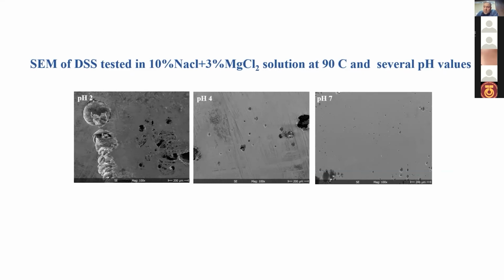Generally, corrosion resistance of stainless steel is achieved by dissolving a sufficient amount of chromium in iron to produce the coherent, adherent, insoluble, and regenerating chromium oxide protective film on the surface. And this passive film of chromium oxide formed in the air at room temperature is only about 1 to 2 nanometers. And the pitting corrosion is the result of the local destruction of the passive film and subsequent corrosion of the steel underneath this layer.